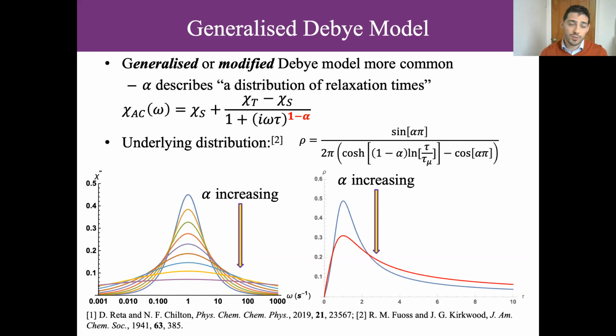So for the molecules that have their anisotropy perpendicular to the field, you're basically not magnetizing them, because if you have such a strong anisotropy, their magnetic moment along this direction is going to be nothing. So essentially those will have very quick relaxation times, because they're not really magnetized. So it is partially to do with this, yes. But the majority of the things you're actually measuring are aligned with the field. So that is part of it.